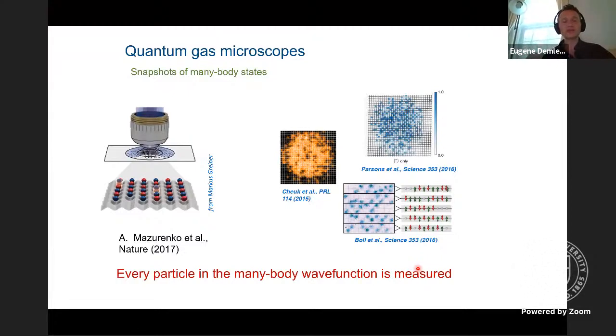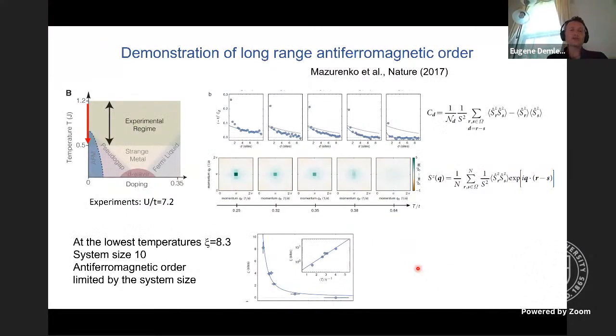But let me start with the way people started thinking about the analysis of the system, starting from the conventional standpoint. The first question was, if we're exactly at half filling, there is one particle per site. That's where we have the antiferromagnetic state. So can we characterize the onset of this antiferromagnetic order, just classically anti-aligned spins? The first thing they measured was just the 2-point correlation function. This is a result from Markus Greiner's group.